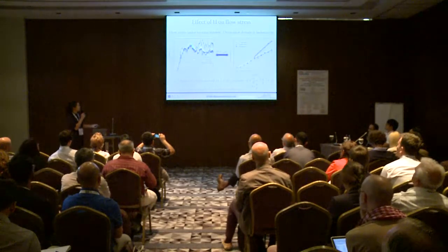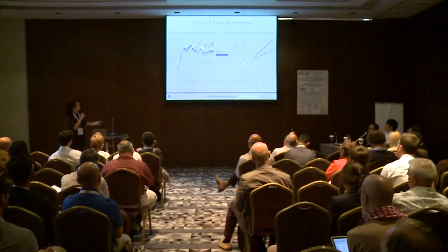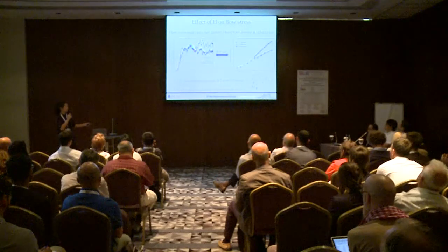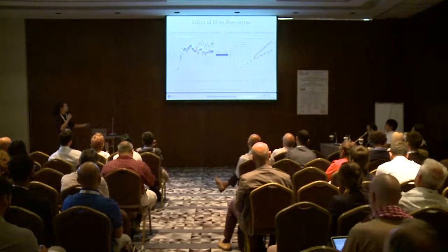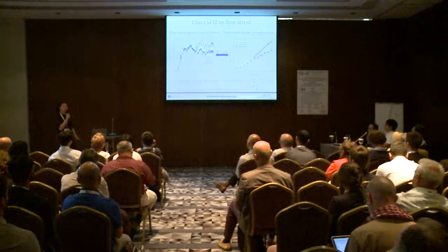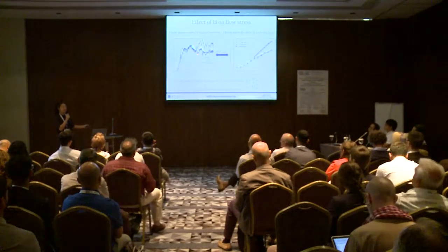We can see that the flow stress at small deformation is almost identical, while at large deformation, hydrogen starts to reduce the flow stress. This is because at very small deformation the plastic zone is really small, and only at large deformation, when the plastic zone is comparable with the specimen size, do we see the influence of the hydrogen.